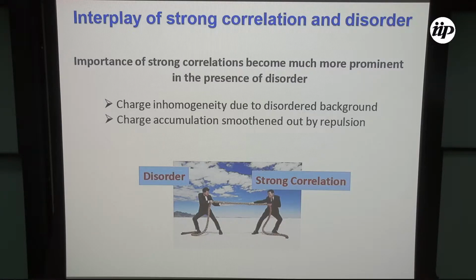in the sample. In order to physically understand what's happening, there are two phenomena occurring. One, disorder, which wants to make the system inhomogeneous with charge puddles everywhere. But if you have strong repulsion between the electrons, they would not like charge to accumulate. So they would smoothen out the charge accumulation and try to smear out the charge inhomogeneity. As a result, they compete with each other very strongly.